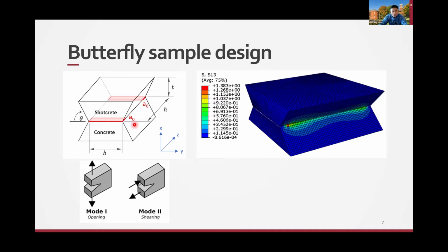One of the ideas is to make this butterfly sample, as you have seen here. As you know, for concrete, a pulling or tensile test is not that straightforward. There are many complications. So one way to avoid many issues is to make this butterfly. And for the fracture test, like a traditional fracture mechanics mode 1 or mode 2, you put a notch at the interface, so it can do this fracture mechanics testing. In the red here, we put some tape between the two layer materials, and there will be a notch or crack, a simulation of a crack, before the test.